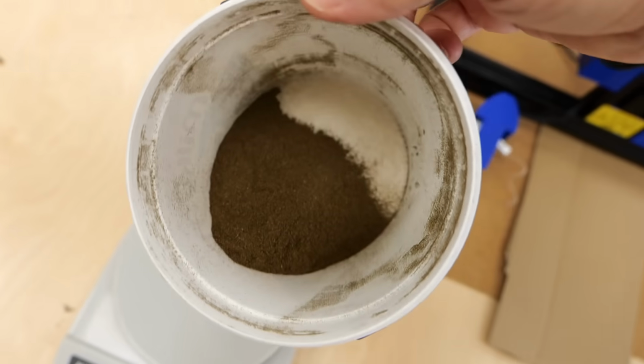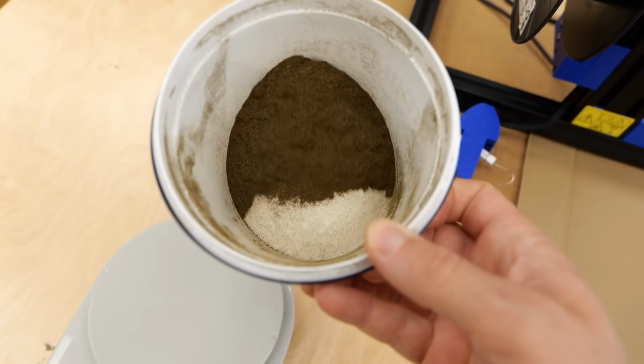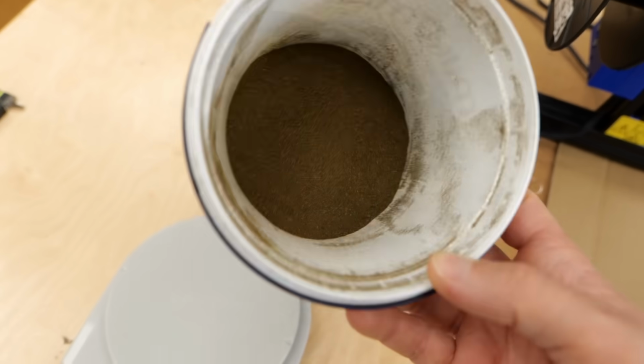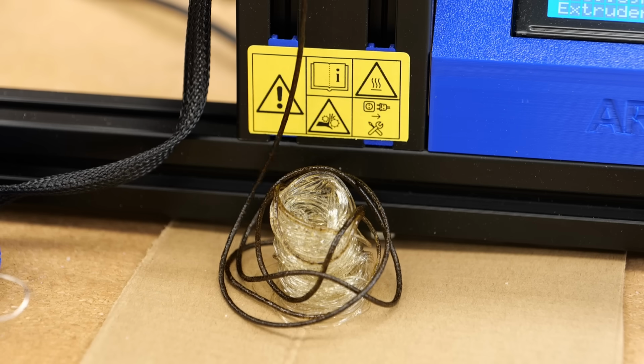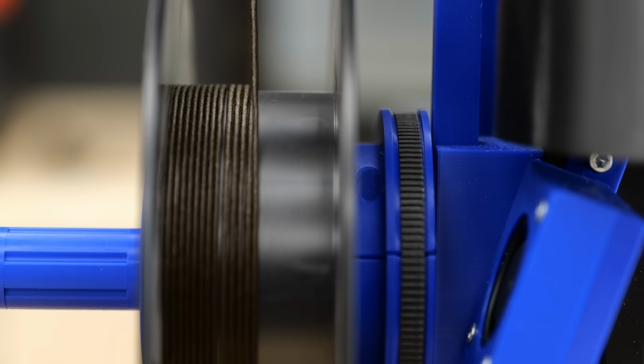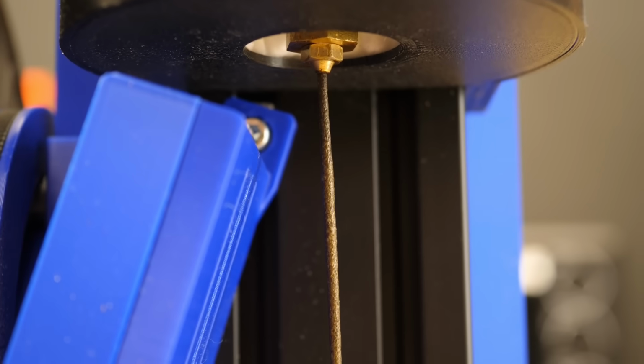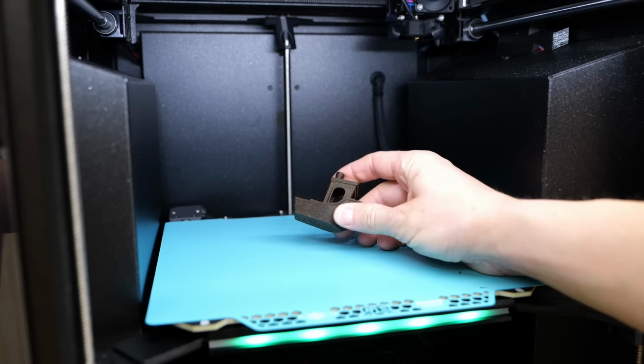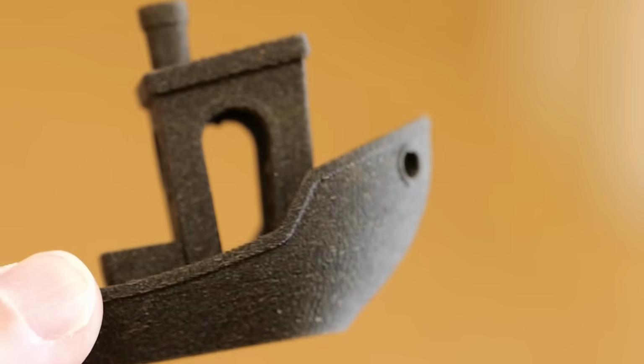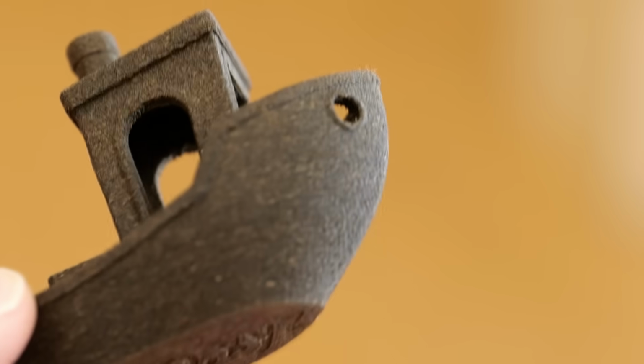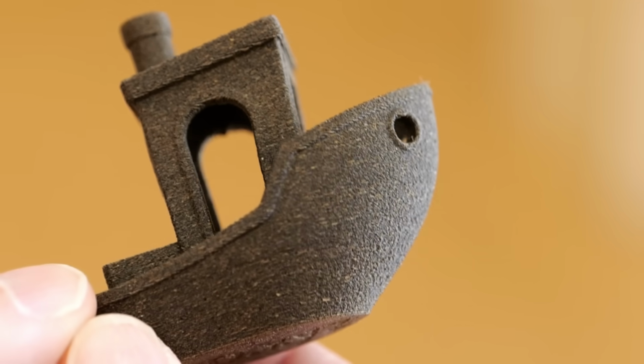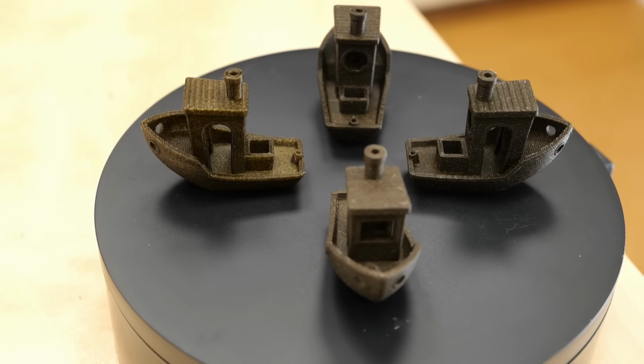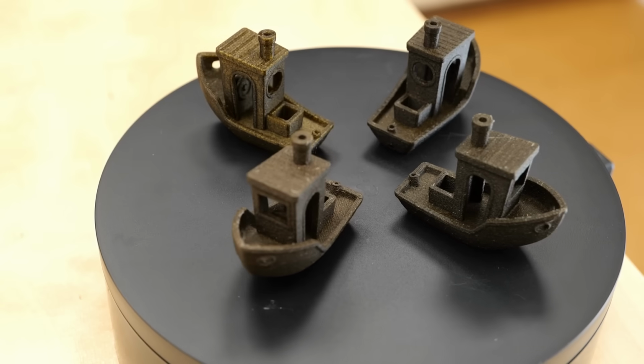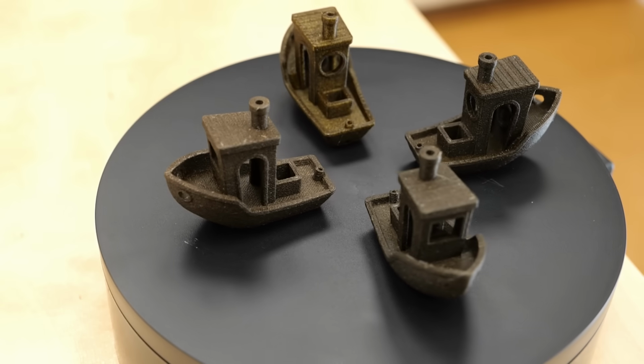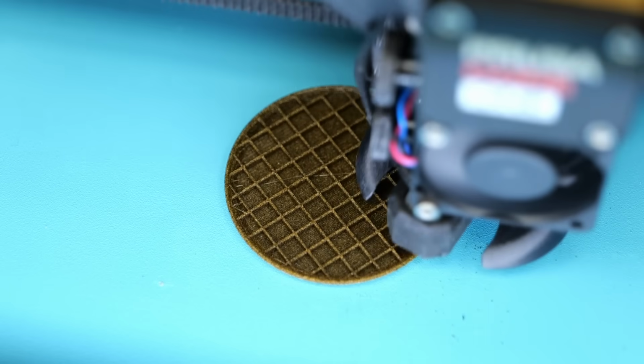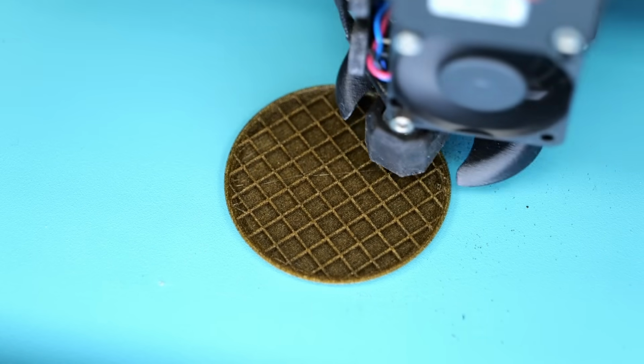So I did my final batch at 20% cow poop by weight, which, just looking at the ratio in the bucket, is quite a bit. Besides having a substantial amount of poop in my material, the extrusion went great until it foamed up again, but it left me again with enough material for a benchy and later my test parts. The texture of the print looked expectedly even a little bit rougher than previously, but it printed great even through the fine nozzle. The print results with the material made from PLA powder really impressed me and showed that if I work with pulverized plastic, I can now even experiment with different compounds on my inexpensive filament maker.